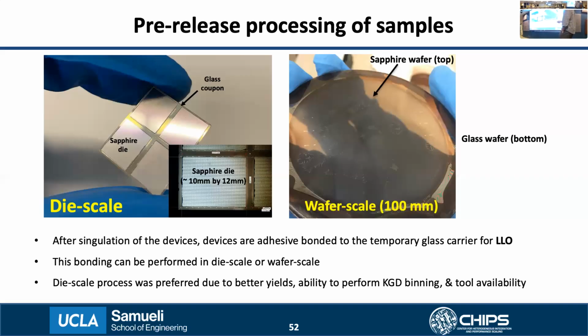Once the sapphire with the singulated devices is bonded to the temporary carrier, the next step is to perform the gallium nitride laser lift-off process for detaching the LEDs from the sapphire substrate onto the temporary carrier. Before I continue with this particular process, I will talk more in detail about some of the work we have done to improve the yield of the gallium nitride LLO process that is needed to release the LEDs from the sapphire. Before that, any questions?